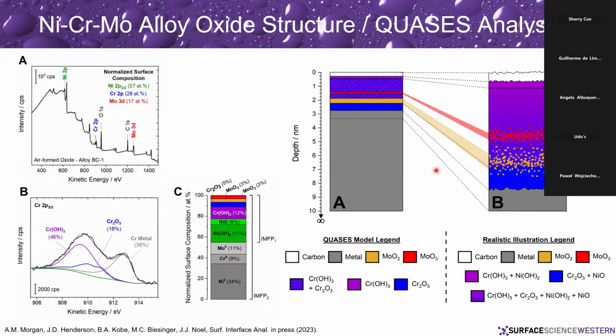Now, this is not an easy analysis. This was probably a year or so of Adam Morgan's work that he put in to try and pull all this stuff out, as well as doing things like depth profiling in TOF-SIMS and Auger and those sorts of things as well. Angle resolved type analysis can get involved in this sort of thing as well. And so it's a complex thing, but if your goal is to really pull apart what's going on at the surface of a system that you're looking at, these are the sorts of things that you can do.